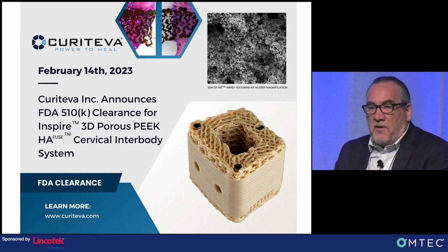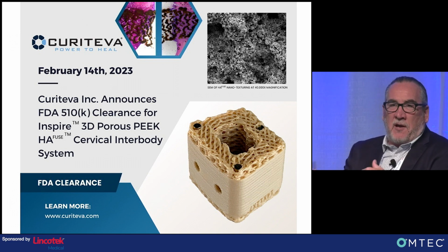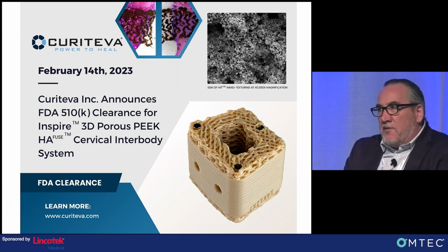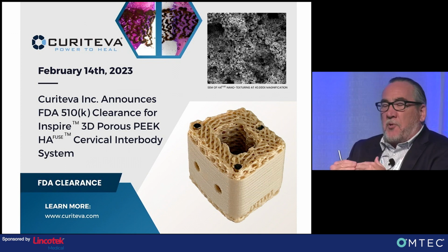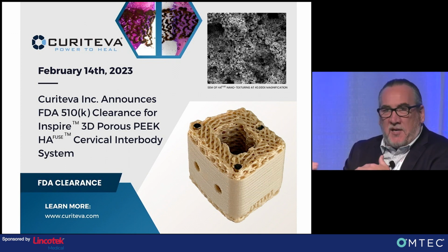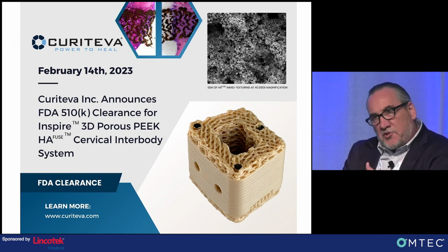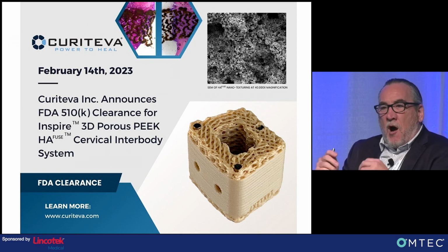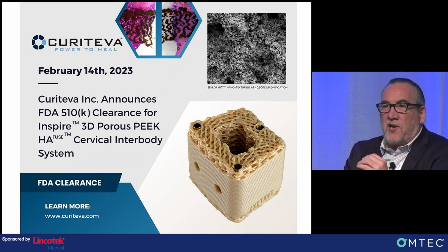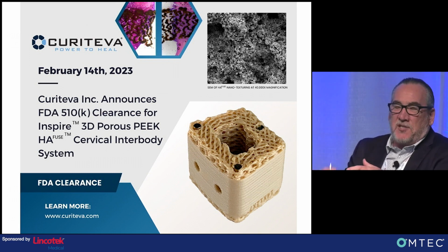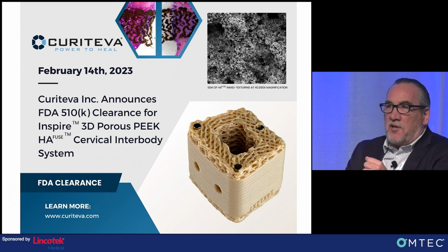So the strength values here, and I'll say one thing as a lead-in, the properties of PEEK are very dependent, as I said, on temperature, rate of extrusion, rate of deposition. Our ability to control, with the filament that we got from Evonik, going from the amorphous to the crystalline state is very key to making sure that the Z-layer bonding is there, where you're taking your footprint and then you're making a third dimension out of that. That's very instrumental in getting the strength values and the toughness values that we got.